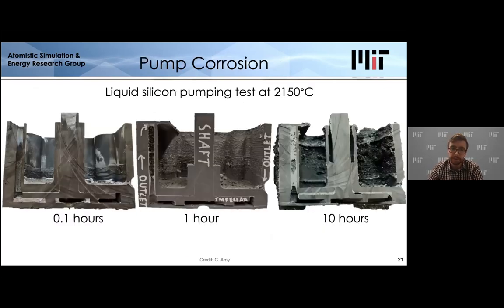Unfortunately, when we went to design the pump, which is an essential part of this system and probably the most challenging part as well, we realized, okay, things aren't quite as simple as it seemed. So these 3 pumps are actually 3 separate experiments, which are operated at a temperature of around 2150 degrees Celsius for different periods of time. And what we saw in these 3 cases is that although we were able to pump relatively well for short times, 0.1 hours to 1 hour, when we went to the 10-hour case, you can see this gap right here. It's significantly thicker in this case than the other two cases.